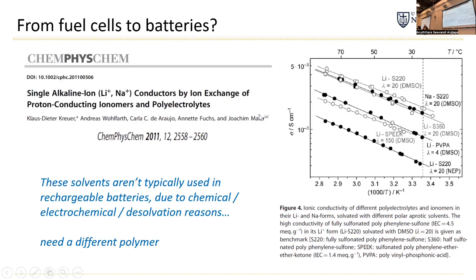What people have found is that, as you can see from the conductivities here, they're around 10 to the -3 Siemens per centimeter. That's good, getting close to that of a liquid. The problem is that the solvents they have to use in order to get this high conductivity are not compatible with most battery chemistries.